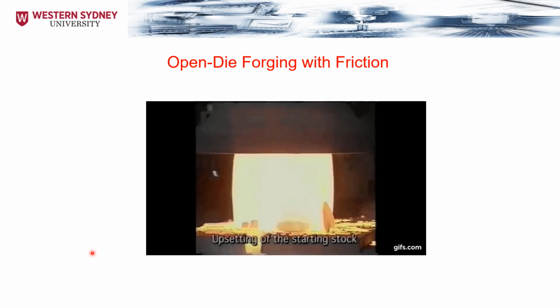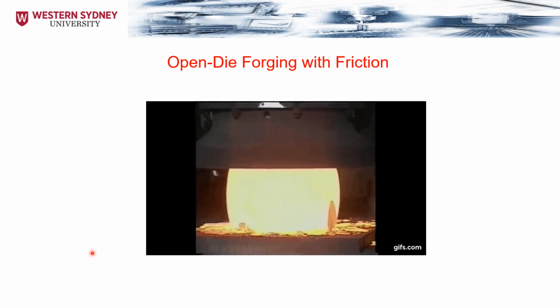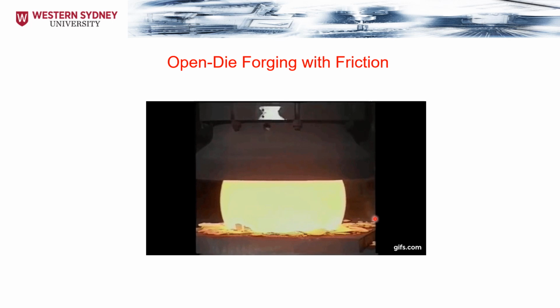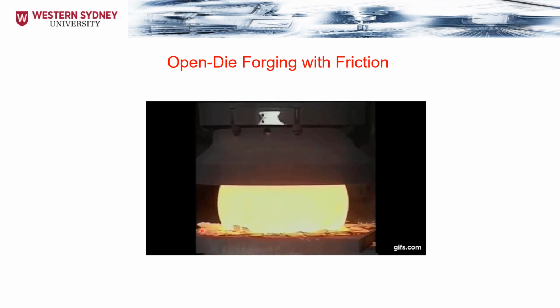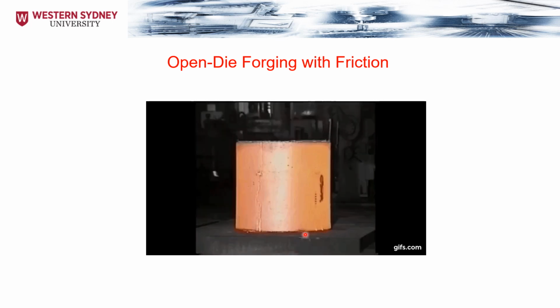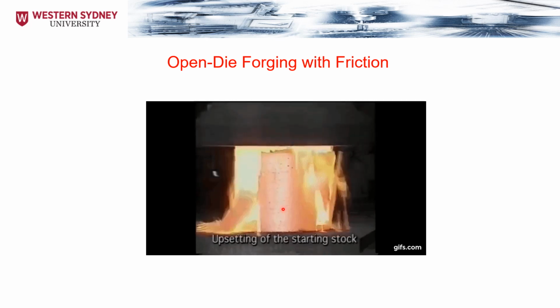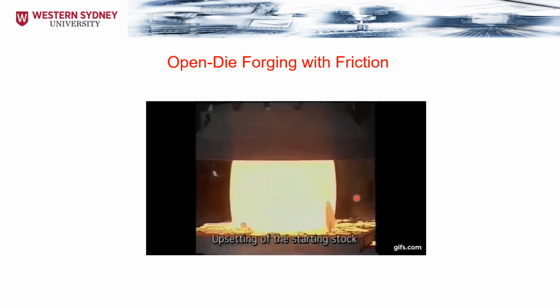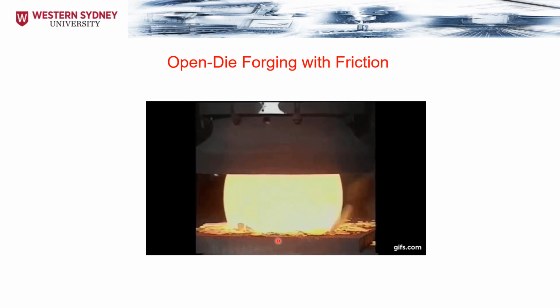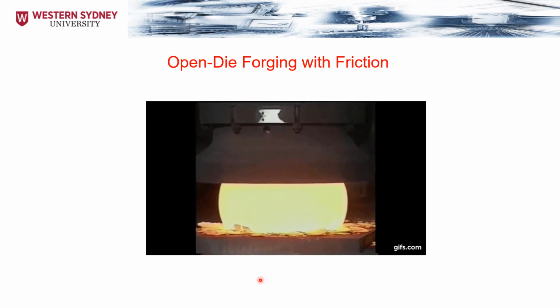So that's what happens in the case of open die forging with friction. You can see that the barrelling is happening here. The material that has dropped out from the specimen is what we call the scales, and this happened due to the oxidization of the surface due to the high temperature.